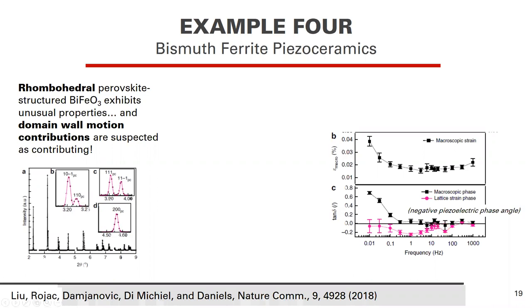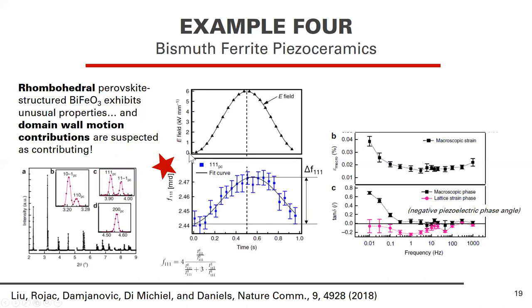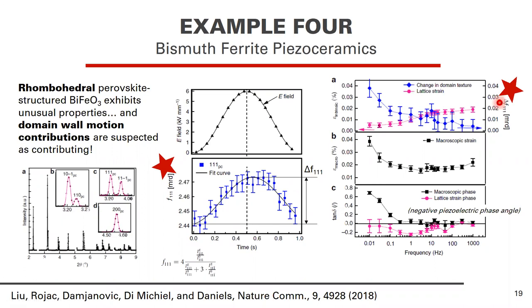And so the John Daniels group with Lisha Liu at UNSW then took these samples and applied these same types of experiments. And so you can see a representation of the 111 peak splitting in this rhombohedral based material. And they're applying a sinusoidal electric field and they're tracking F111. So this is the multiple of a random distribution of the polar 111 direction as a function of time and electric field amplitude.